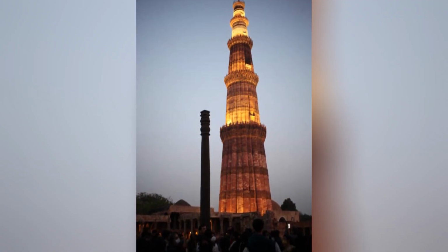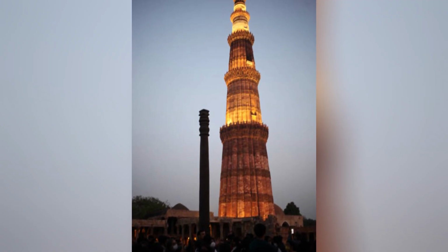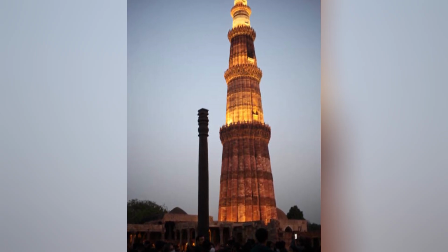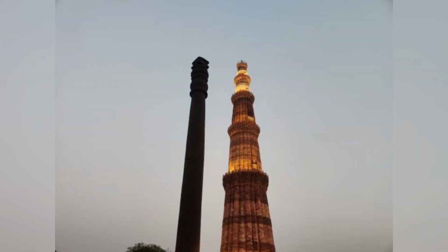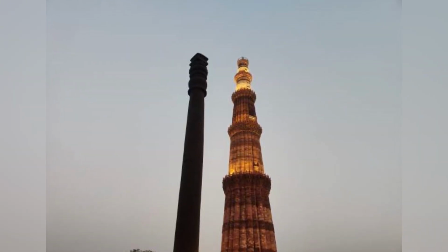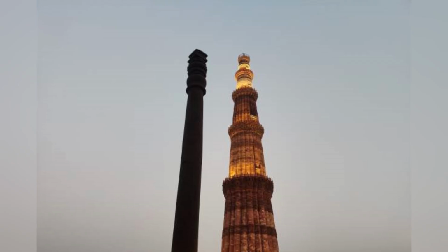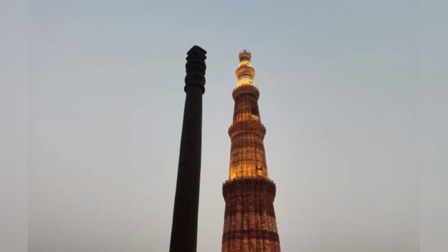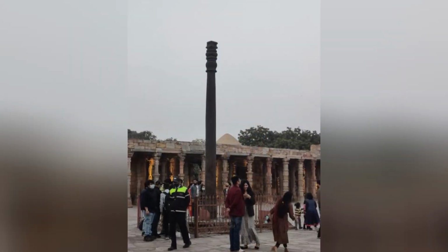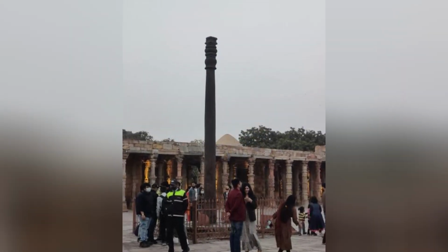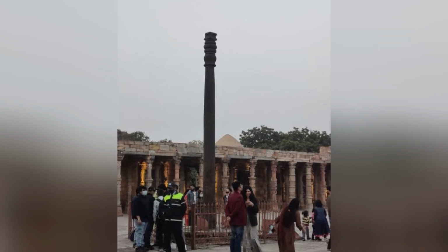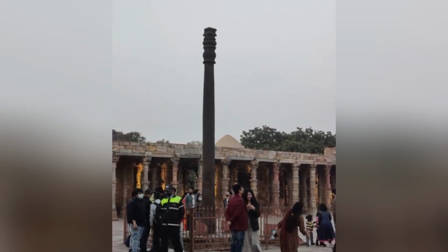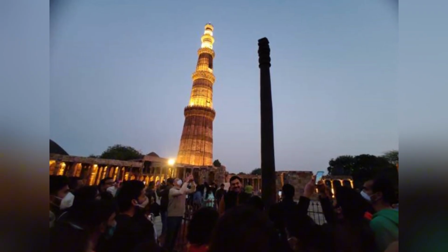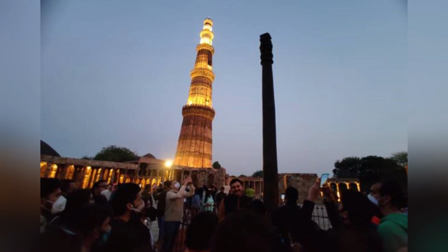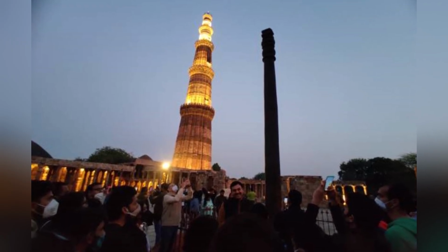The protective film, which Balasubramaniam identified as a layer of iron hydrogen phosphate hydrate, a mineral compound with the chemical name misawite, was formed through a specific chemical reaction between the phosphorus in the iron on the surface, and the moisture and oxygen in the atmosphere. The phosphorus, which was present in the iron as a result of the specific ore that was used in the smelting process, reacted with the iron and the atmospheric moisture to form a thin, dense, adherent film of iron hydrogen phosphate hydrate that sealed the surface of the iron and prevented further contact between the metal and the corrosive atmosphere.